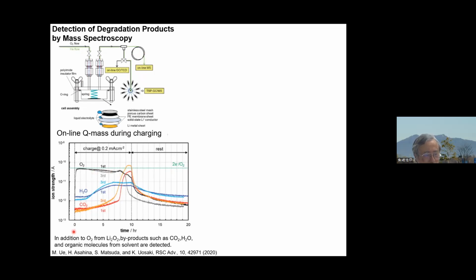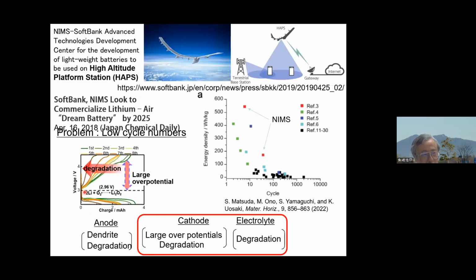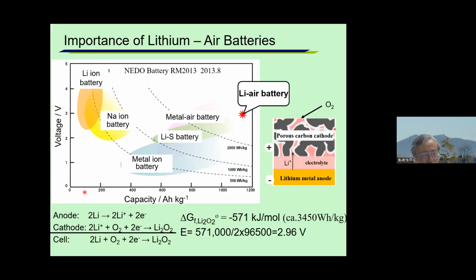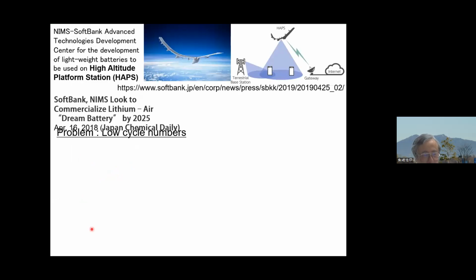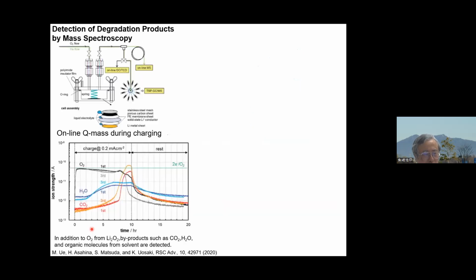So during the charge, actually we generate oxygen because of the reaction. During the charge, Li2O2 becomes oxygen and lithium plus. If only oxygen is generated, it's good, but we have water and CO2. CO2 comes from the decomposition of the electrolyte or the carbon cathode. So it's bad.